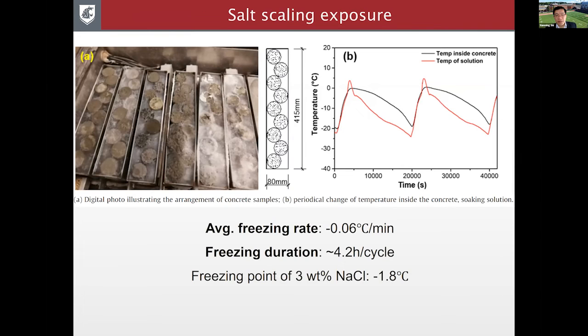So salt scaling test, the cylinders were exposed to this accelerated wet, dry, freeze-thaw cycles. You can see for each cycle, it's about 6 hours, but the freezing duration is approximately 4.2 hours. In other words, the other times of the cycle, the solution is not frozen based on our estimate, knowing that the freezing point temperature of the 3% sodium chloride is about minus 1.8 degrees Celsius. And the freezing rate is also important. As we know, this is an accelerated test. In the real environment, in the field, you probably won't be seeing as fast freezing rate. Therefore, your concrete should last much longer.